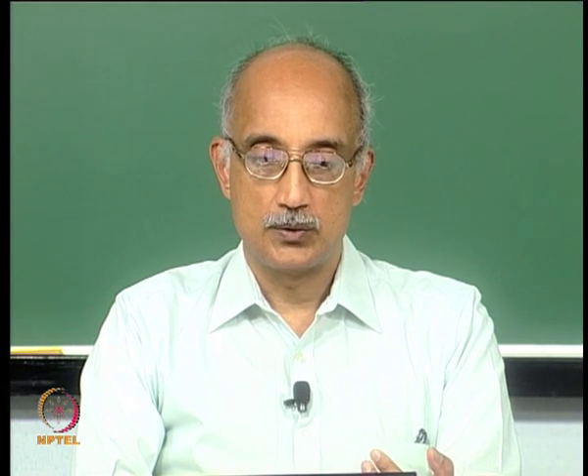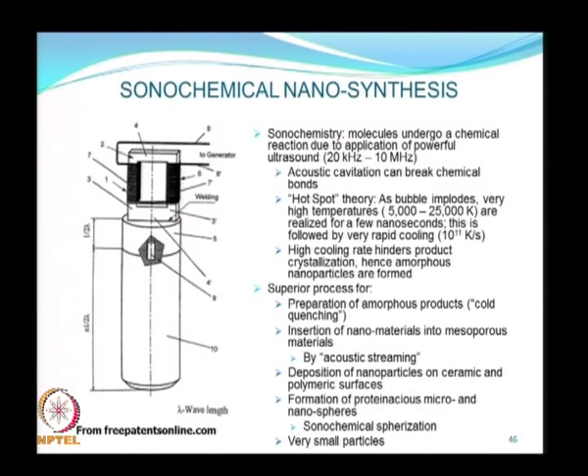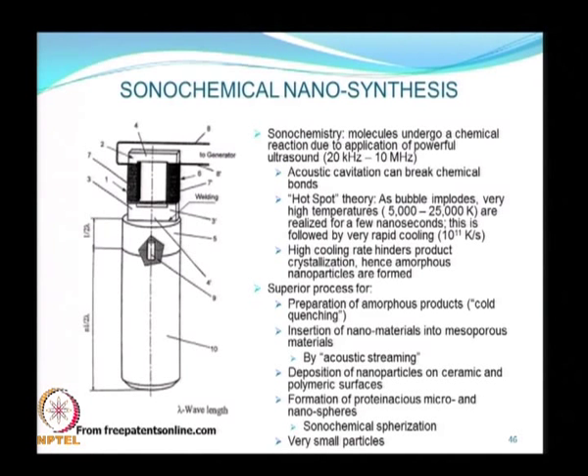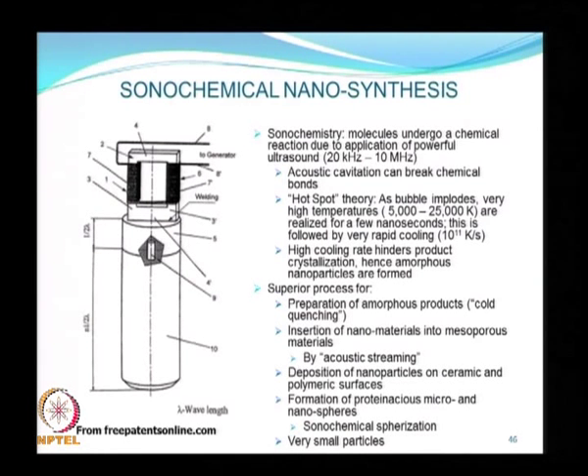According to the hot spot theory, as bubbles implode, temperatures of the order of 5000 to 25,000 Kelvin can be realized for a few nanoseconds, followed by very rapid cooling. During the time when these high temperatures and pressures are in effect, chemical reactions can be driven several orders of magnitude faster than they would otherwise proceed. This acoustic cavitation effect can break chemical bonds and make chemical reactions run very, very fast, thereby intensifying the process by which nanoparticles are synthesized.